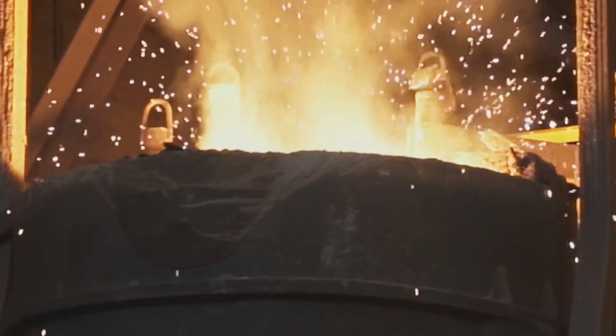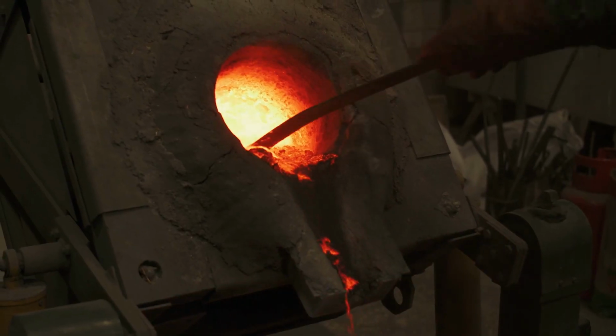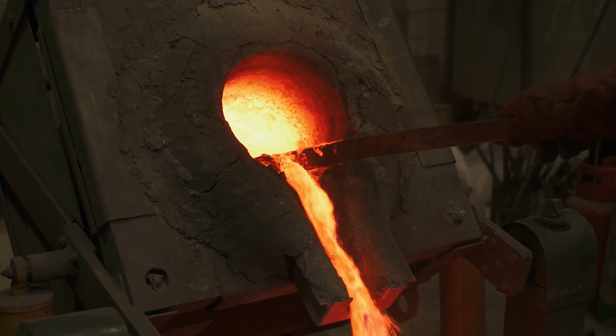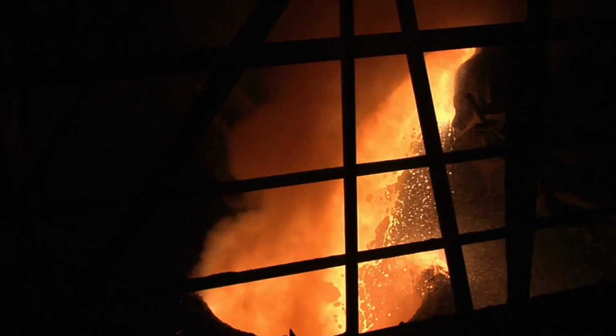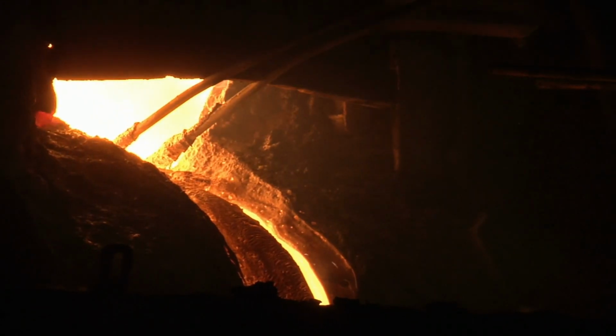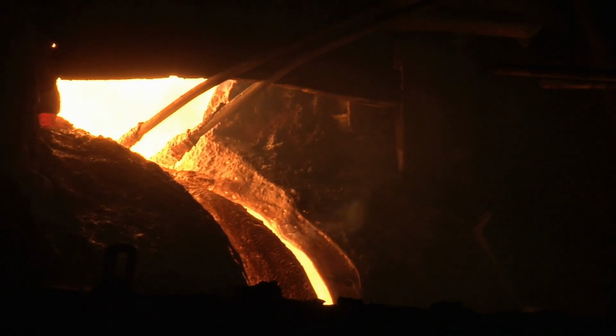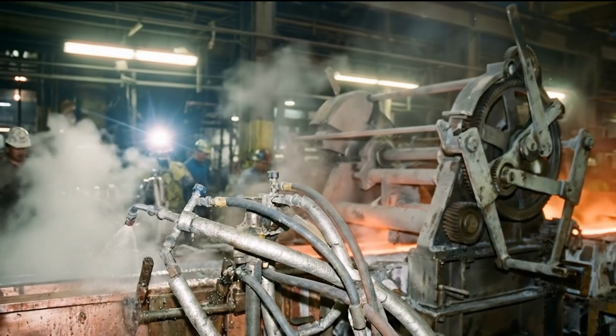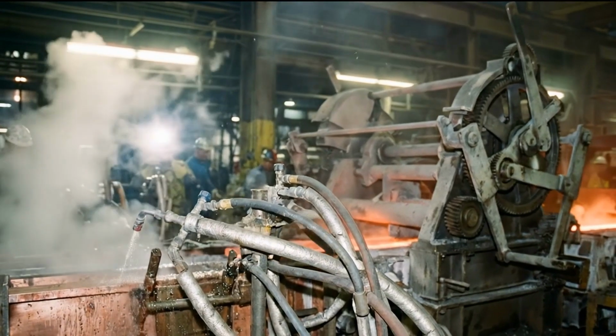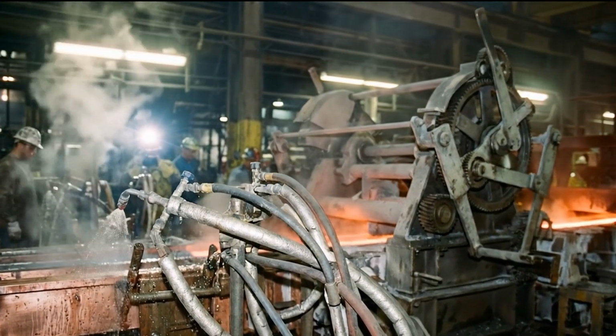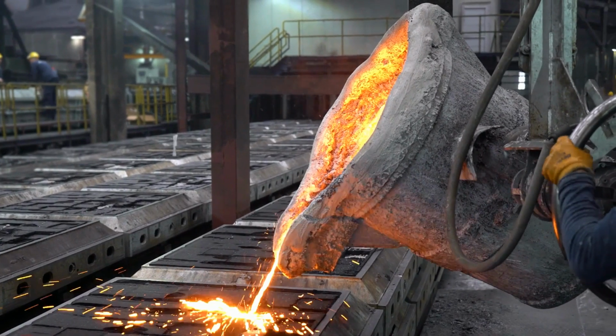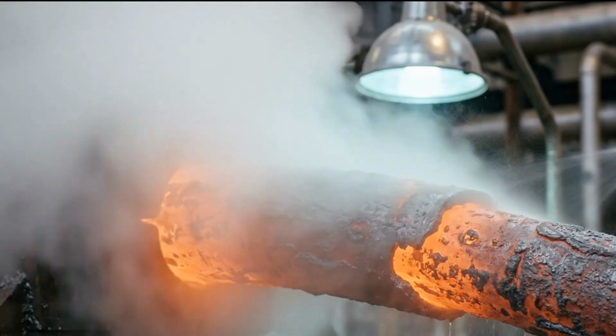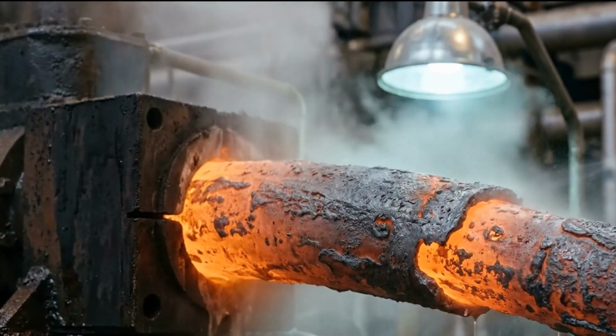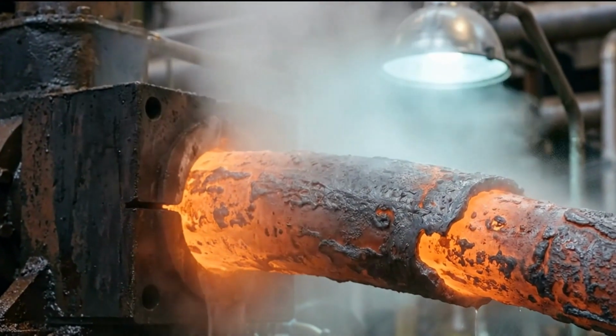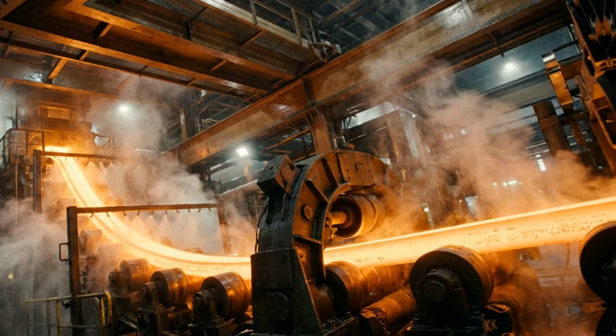The machine begins with a ladle, a refractory-lined steel vessel holding anywhere from 100 to 300 tons of liquid steel at around 1500 degrees Celsius. The ladle sits above a tundish, which is a distribution vessel that acts as a buffer and flow controller, feeding liquid steel at a controlled rate into one or more water-cooled copper molds below it. The molds are the critical component. They're not static. They oscillate vertically, several times per second, to prevent the solidifying steel shell from sticking to the mold walls. The outer skin of the strand solidifies in the mold. The interior is still liquid.